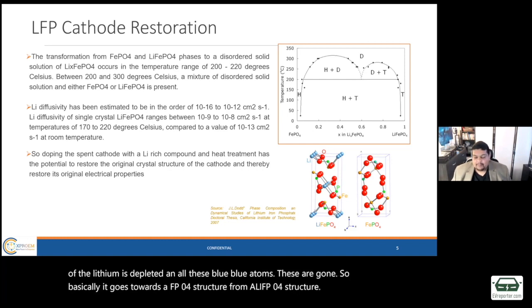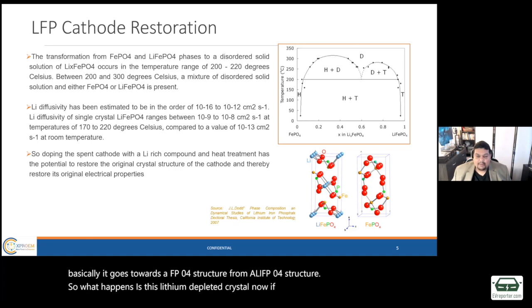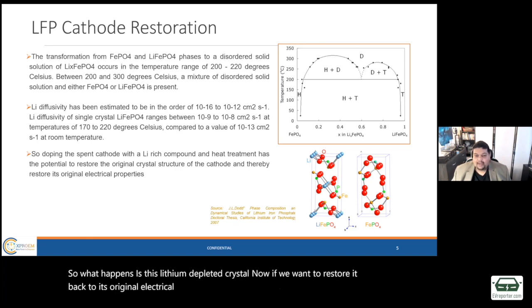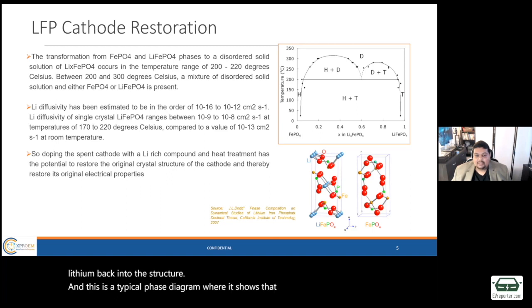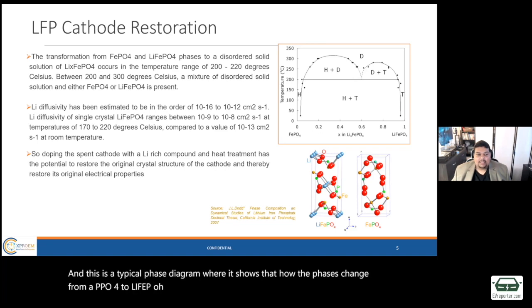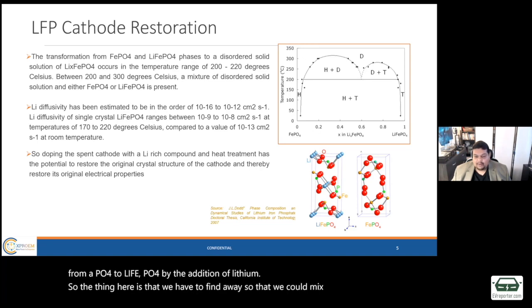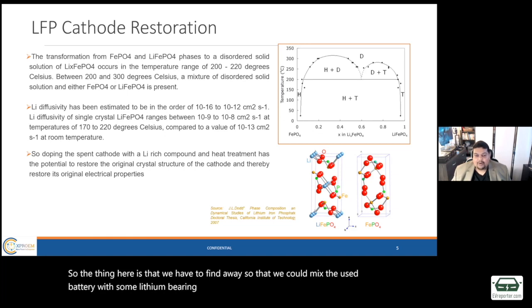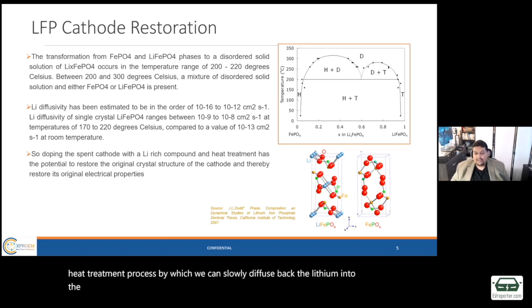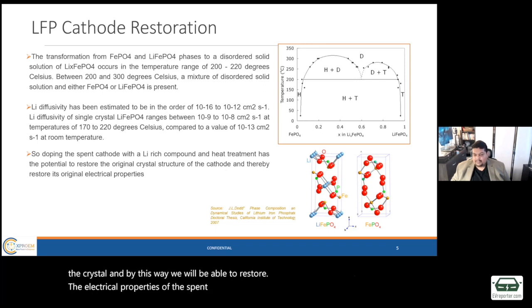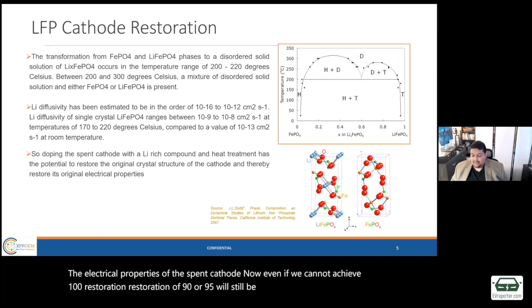So if we want to restore this lithium depleted crystal back to its original electrical properties, we have to find a way to bring the lithium back into this structure. And this is a typical phase diagram that shows how the phases change from FePO4 to LiFePO4 by the addition of lithium. So we have to find a way to mix the used battery with some lithium bearing compound, and then find a heat treatment process by which we can slowly diffuse the lithium back into the crystal. By this way, we will be able to restore the electrical properties of the spent cathode. Now, even if we cannot achieve 100% restoration, a restoration of 90% or 95% will still be a very welcome step in the right direction.